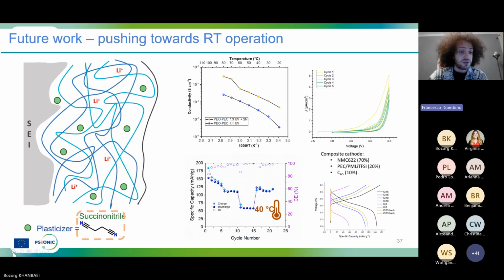This plasticizer that we are currently testing is succinonitrile. We observed an increase in the ionic conductivity compared to the membrane without succinonitrile, and also the electrochemical stability window is really good due to the stability of the cyano group present in this molecule. Also, we performed some preliminary tests with an NMC-based cathode at 40 degrees. And as we can see, there is good specific capacity reached at C over 15. We have a specific capacity of 130 milliampere hours per gram. So we are currently testing this membrane and further characterizing it in order to achieve operation at lower temperature with NMC-based cathode.